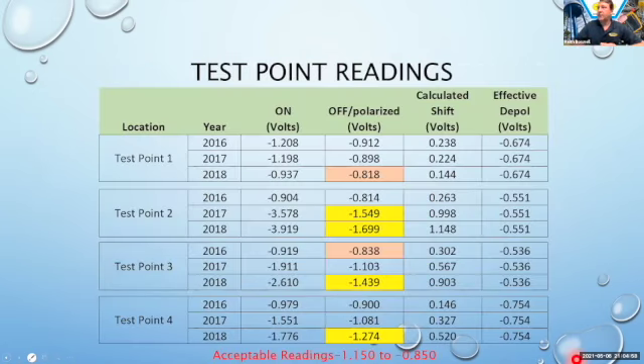So this is what you typically would see during an annual type inspection, where we have our different test points 1, 2, 3, and 4, and different varying years of readings, in this case 2016 to 18. Here we have our on potential, so this is with our cathodic protection on. And then we have our off, or that instant off, or the polarized potential. This is when we interrupt those current sources, and as soon as those turn off, we record what that polarized potential is.